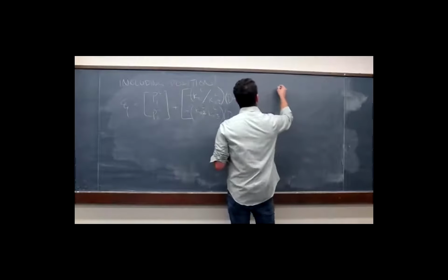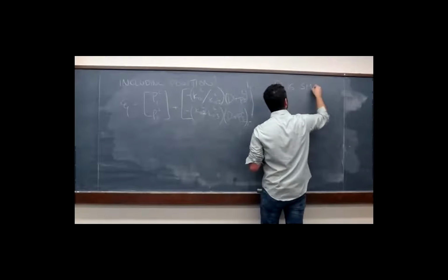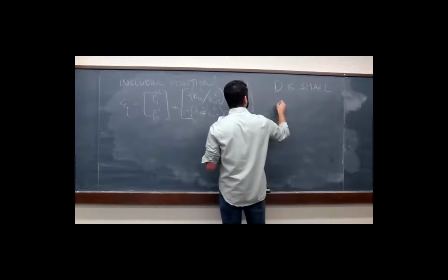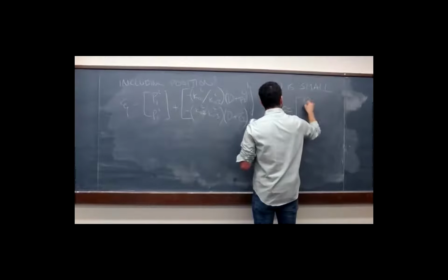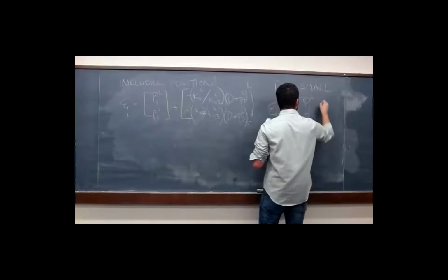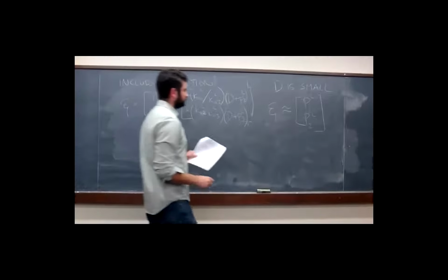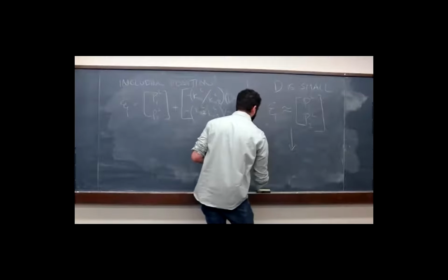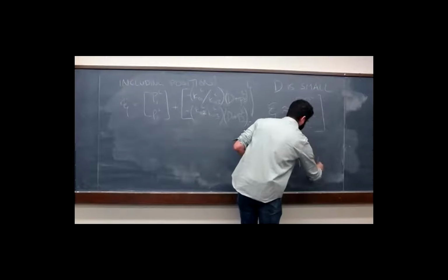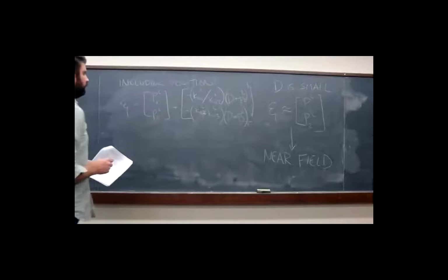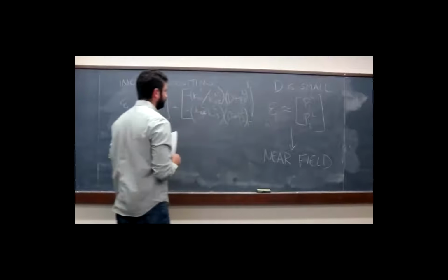What we find is that the intercept is about equal to just the position terms in the transverse plane. So when we're close, this term becomes dominant. What we call this, for these experiments, is the near field. So when we're working in the near field, where our diffracted intensity intercepts the detector is dominated by the positions of the crystal during a diffraction event.